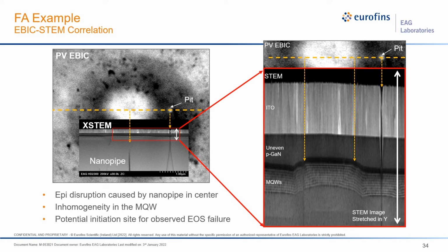And then what's of really big interest is actually this pit here, right? So we have a pit in the ITO, and you can actually see that the ITO extends down almost now into the multi-quantum well. And this is where our electrical junction is. So we actually have this very sharp V defect type pit. It's got conductive material that actually gets down further into the sample. And so this is a really good candidate, or a highly likely site of where, if you're reverse biasing this device with significant energy, you could get breakdown to occur and potentially diffusion of this material down and cause the short in the device at this location. So using SEM-EBIC, we get a little further insight into why we got such catastrophic failure in the case of our stress test on our other LED.